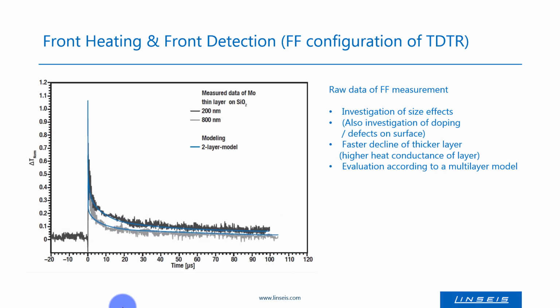This is what the TD-TR measurement looks like for two molybdenum thin film layers on the same substrate, but with different thicknesses. What we see here is the heating pulse at time 0, showing the normalized temperature peak and the ongoing temperature decrease of the heated spot over time.